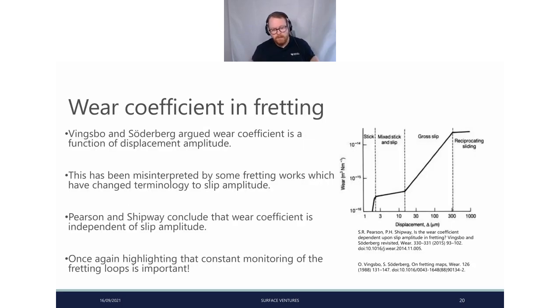So, wear coefficient in fretting. What we have here on the right is a graph taken from a Pearson and Shipway paper, relatively recent, 2015, where they were looking at wear coefficient depending upon slip amplitude. This is something that has been talked about a reasonable amount in different fretting literature, referring back to Vingsbo and Soderberg, who stated that wear coefficient is a function of displacement amplitude. However, there's been some misinterpretation to say that this is then slip amplitude.